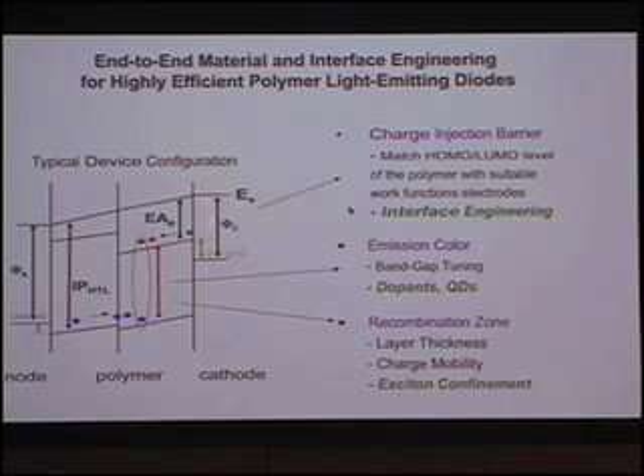But then our work here, because I am limited by time, I only try to focus on some development of the hole transport layer. Also some of the interface of the so-called conjugated surfactant at the cathode area allows us to inject holes and inject electrons very efficiently. So when we find a suitable complex and recombine in the middle range in here, they can dramatically enhance the device performance.